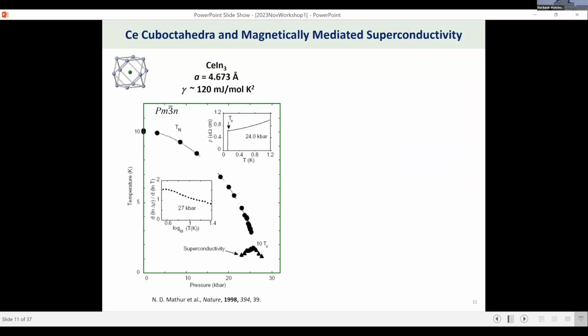So Alan Shea posted this list. Cerium indium 3. And that was something that really started me thinking about this quite a few years ago, in the beginning of my career, actually. This is the cerium indium 3, with a gold copper 3 structure type. Essentially, you apply a pressure and you have an antiferromagnet that becomes a superconductor. That's great. And that's a cerium environment where you have 12 neighbors. So that's a cuboctahedron.